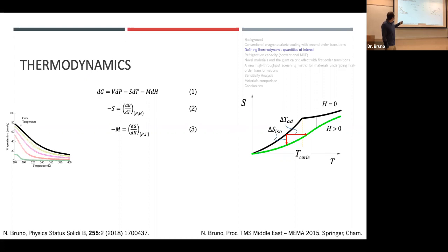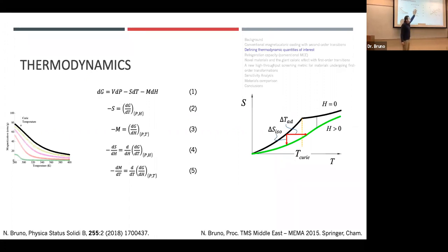So in an isobaric process where we have constant pressure, our dP is 0, and at constant field, our dH is 0, we can define our entropy by dG/dT, the derivative of Gibbs free energy with respect to temperature. We could do a similar thing for finding our magnetization with Gibbs free energy. It's dG/dH, but that's in an isobaric, isothermal process. And then we can do some math trickery to derive something called the Maxwell relationship. The Maxwell relationship is when we take the derivative of S with respect to H and M with respect to T, the other thermodynamic variable, and we see that both of those quantities are equal to the same thing. It's like Schwarz's mathematical theorem or something says that the order of cross differentials doesn't matter.